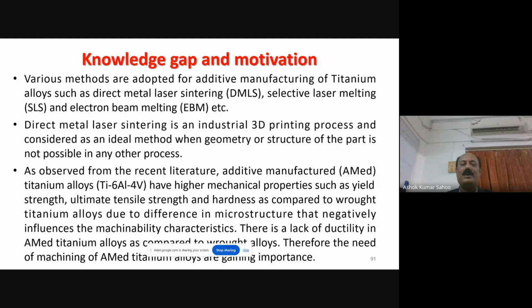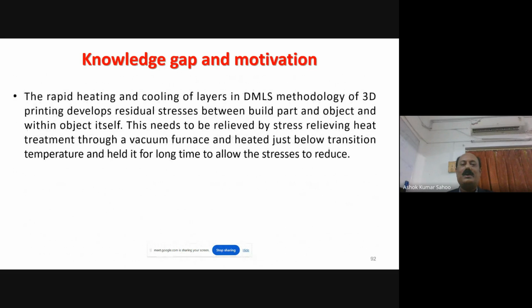In addition to this, various methods are adopted for development of the additive manufactured titanium alloy through the direct metal laser sintering process. Okay, as observed from the literature, additive manufactured titanium alloy has higher mechanical properties such as yield strength, ultimate tensile strength, and hardness as compared to the wrought alloys due to difference in microstructure that negatively influences the machinability. So there is a lack of ductility in additive manufactured titanium alloy as compared to the wrought alloy. Therefore, the need for machining of additive manufactured titanium alloys is gaining importance nowadays.